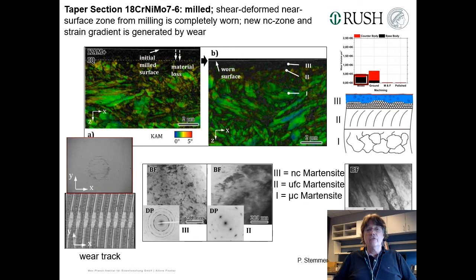So after wear, this is the surface here in this area, and below that you see so-called no counts. The black area means no counts, meaning the deformation is so large that we are not able to measure it by EBSD. And these strains here were not there before. So they have been generated in this martensitic material during the wear process.